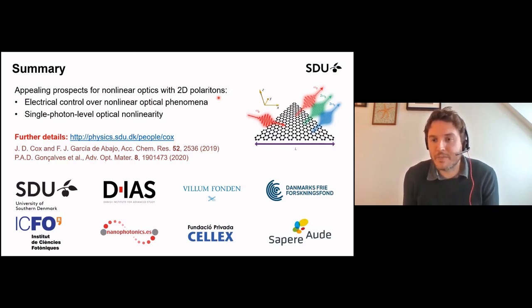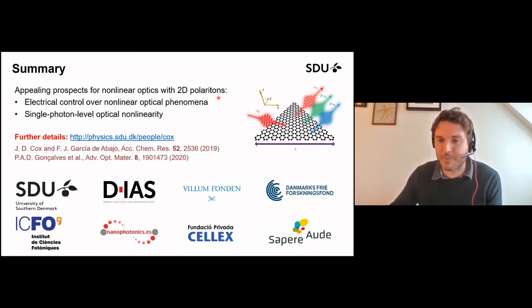I mean, as a theorist, to me, the doping is sort of a number that goes into the simulation. But I'm always trying to use realistic values. There are upper limits to how far you can push that, how many electrons you can really cram into a 2D graphene sheet. So usually we stick to the Fermi energy up to 1 eV or so. That's already kind of exotic. So chemical doping can give you higher energies, but then you start to sacrifice the active tunability.